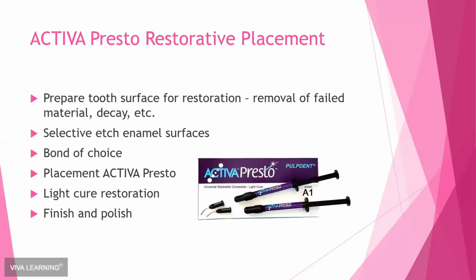In looking at the Activa Presto, very similar as far as how you're going to prepare and place that material. Prepare your tooth surface, selective or total etch, bond of choice, placing the Activa Presto. Again, in your 2.5 millimeter increments, you're going to light cure this restoration and then finish and polish. This material finishes with a very high, very aesthetic gloss.